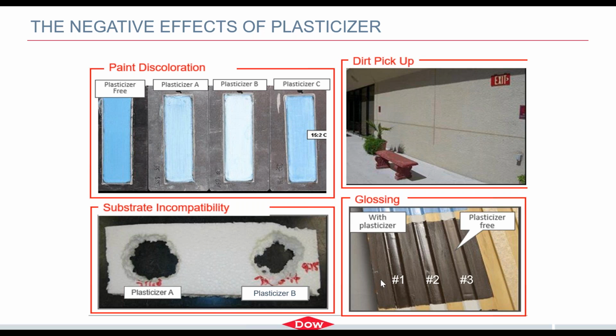And the last property I'd like to highlight goes back to paint, if you're applying that over top, and that's with the glossing look. So here we have 3 different sealants, 1, 2, 3. Dried the sealants, painted over with a flat brown paint. As you can see with sealant 1 and sealant 2, there is this sheen to it, the light reflection. So now your nice flat paint has a gloss to it. So if it's right next to something that's painted with the flat that doesn't develop a sheen, it is just not good looking or aesthetically pleasing. Whereas in sealant 3 here, there's a plasticizer-free sealant, and as you can see, it remains a flat paint. There's no interaction of plasticizer migrating to the surface.